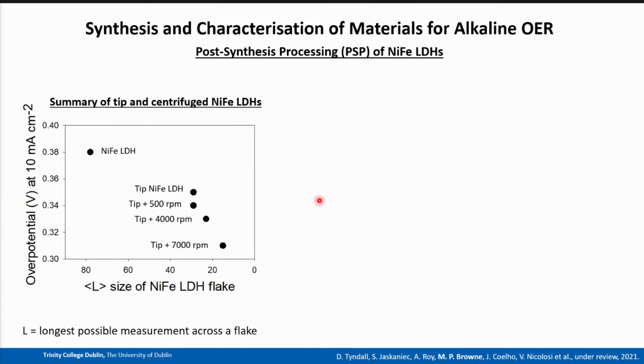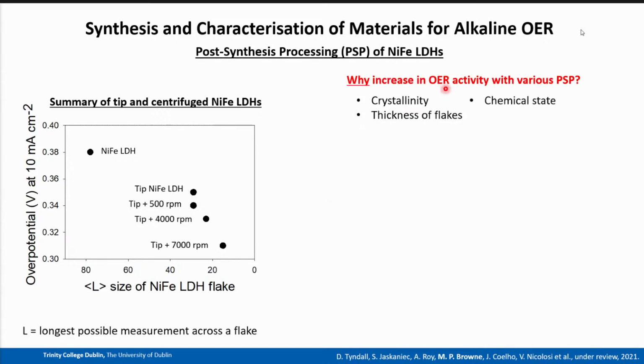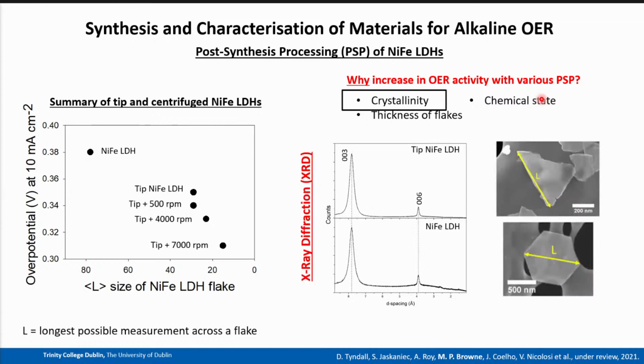So as we are all chemists and physicists, we wanted to try and understand why this is happening. We just didn't want to know what's happening. So we wanted to try and rule out a few chemical changes that could have been happening. So first of all, we looked at the crystallinity of the materials before and after tip sonication, then also the chemical state before and after tip sonication, and then also the thickness of the flakes. So first of all, XRD, or X-ray diffraction, was used to see if there's any changes in crystallinity after tip sonication.